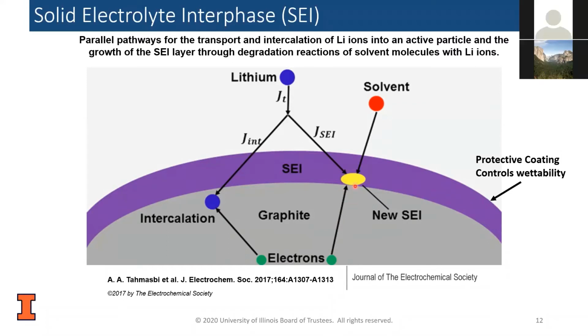Unfortunately, in this case, the electron now is sort of trapped here. It can no longer participate in the charge-discharge cycles of the battery. And as you can imagine, throughout the lifetime of the battery, this SEI layer will continue to grow because we'll still have these two paths. And eventually, you might imagine that we're going to begin to lose capacity of the battery, and that's correct. And also, there may be issues with the layer becoming too thick. And I'll discuss some of those later.